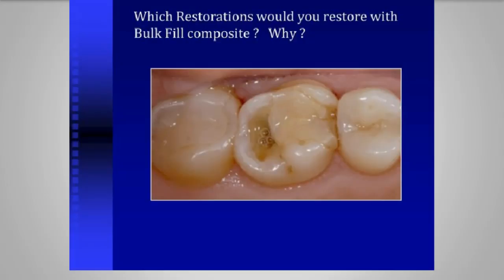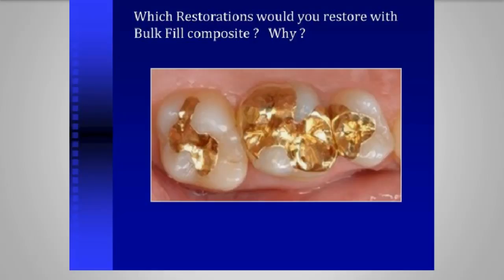When we look at this molar right here, again, by the time we get all this cleaned up and we get a spicule of enamel surrounding this, you can really lasso this with some composites, and pretty soon you're getting into some sensitivity issues. This is probably why I would use bulk fill, especially dual cure. I'd use glass ionomer, or even a sandwich technique in this clinical case right there.